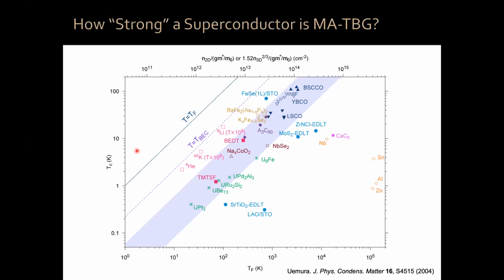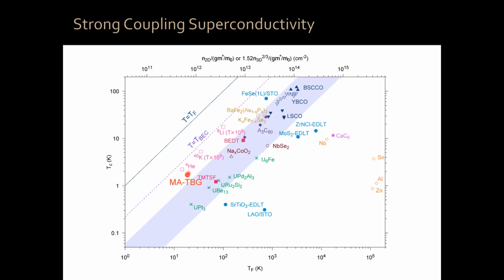Now, where is magic angle graphene in this diagram? It's here. It turns out magic angle graphene has a very high TC, of the order of between 1 and 3 Kelvin, and an extremely small density of electrons. In fact, magic angle graphene is the lowest density two-dimensional superconductor by over an order of magnitude with respect to the next. So the system has an extremely strong coupling, which makes it very difficult that it could be described by BCS weak coupling superconductivity. This still needs to be resolved, but it makes it very, very unlikely.